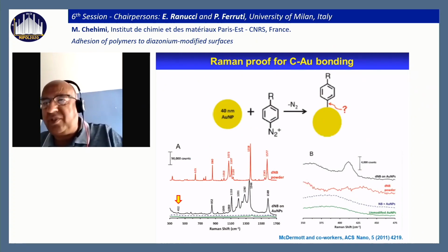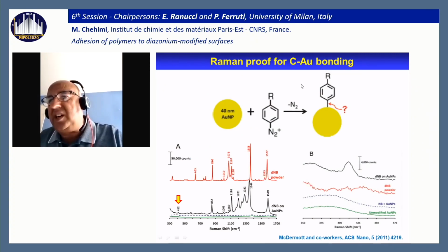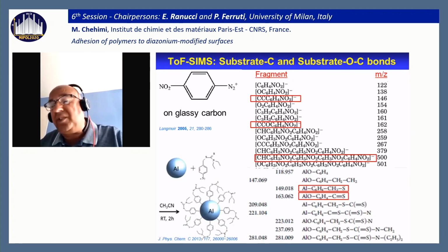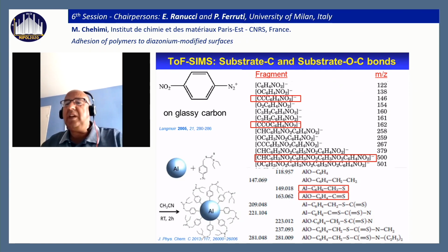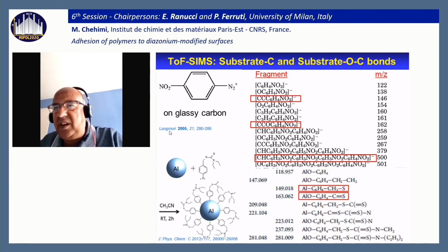By Raman, a group from Canada has demonstrated the existence of carbon-gold bonds at the interface by Raman spectroscopy, by SERS, and by TOF-SIMS, time of flight secondary ion mass spectrometry. This is a very, very powerful surface analysis technique. We can demonstrate the existence of carbon-carbon bonds with glassy carbon or C-O-C bonds, and also the oligomerization of the aryl groups at the surface. Also on aluminium, we can have the aluminium-carbon bond or aluminium-O-C bond at the interface.